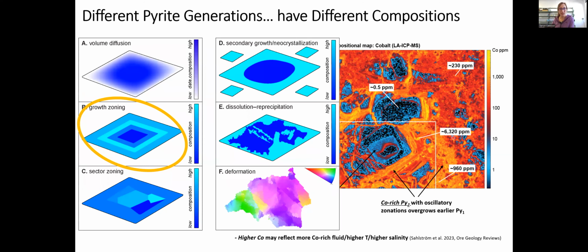This pattern of concentric bands with different compositions looks a lot like what we'd expect from growth zoning, which makes sense. The higher cobalt content in that later pyrite might mean it formed at higher temperatures, higher salinity, or maybe just from hydrothermal fluids that had more cobalt available. And slight variations in the amount of cobalt or in the conditions of precipitation lead to slightly different compositions in each of these bands.